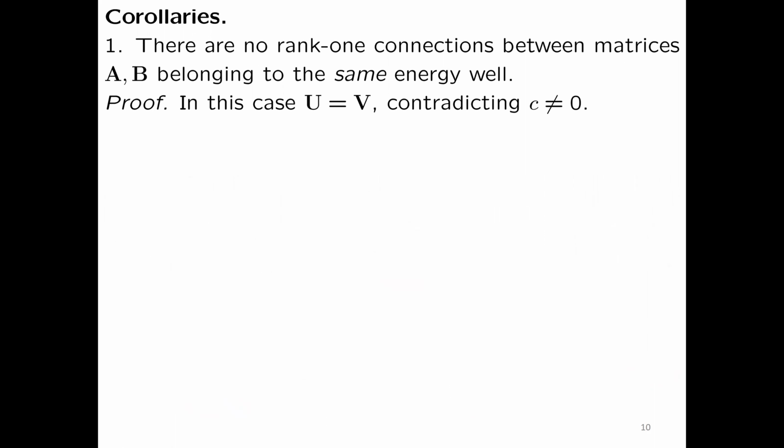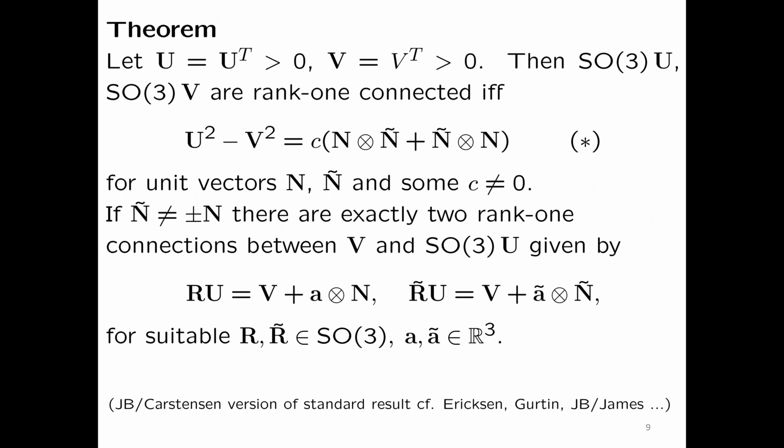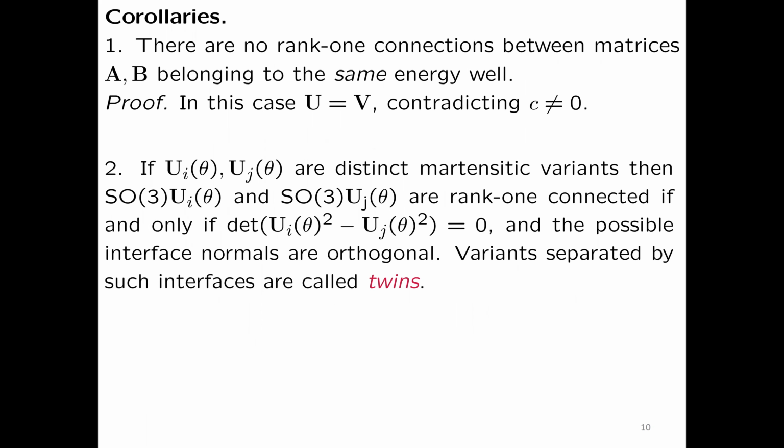So I think that's more or less obvious. I mean, now you've got one, so U is the identity now. So this obviously has to have an eigenvalue 1, because I take something perpendicular to n and to it. And so it turns out to be the middle eigenvalue because of the trace condition.